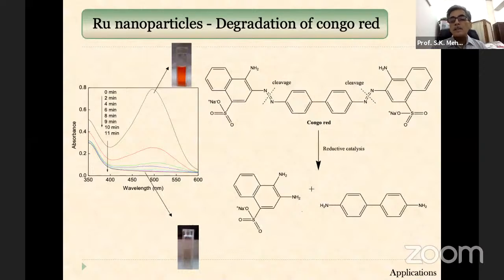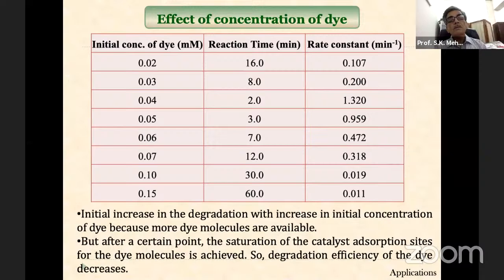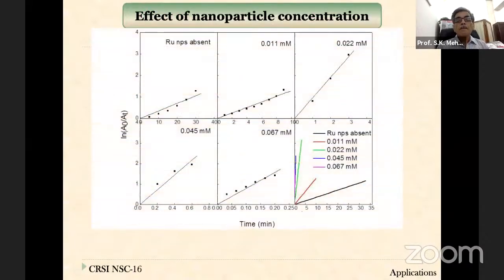So we analyzed how this Congo red, in the presence of this catalyst, is broken into different molecules, and we identified these molecules on the basis of mass spectra also. We also tried to see how much initial concentration of dye is required, what the reaction time is, and what the rate constant is. So all these parameters one can easily study and optimize. So, how much effect the nanoparticle concentration has, how much ruthenium nanoparticles we should use. So all these different studies we also did.